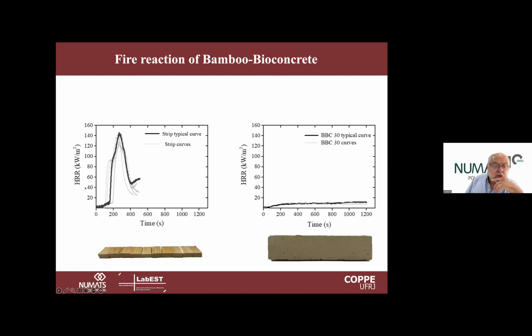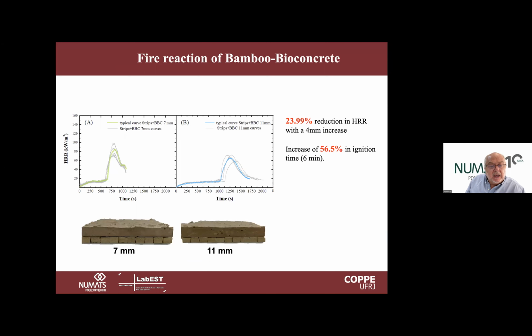So this is the heat release curve with time, just for the bamboo strips. And then with the bioconcrete, we see that very low heat release is observed. This is mainly from the small particles of bamboo on the surface of the radiant flux. But when we use 7 millimeters and 11, we see that 11 millimeters retards the liberation of heat a lot, but it comes after 1,200 seconds. So it reduces the heat release, but doesn't completely prevent the ignition of the bamboo.